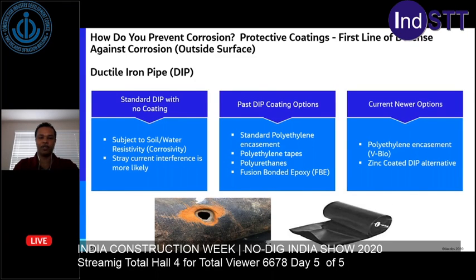So how do you prevent corrosion? Well, really the first line of defense is some protective coatings. Traditionally for ductile iron pipe, in the past, the standard has been using no coating. When you go that route, you're subject to how corrosive the environment is, how corrosive is that soil you install it in, how corrosive is that water. And also you're prone to stray current interference from foreign structures, foreign CP systems, dynamic stray currents, overhead power as well.